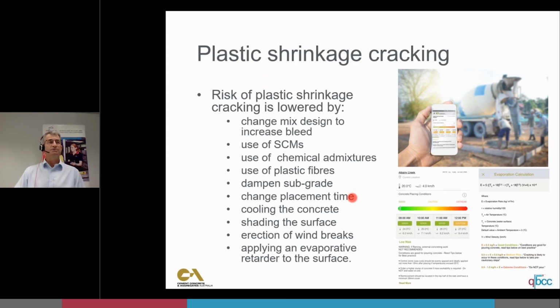So you can also reduce the risk of plastic cracking by all of these things. Having a higher bleed, using SCMs like slag and fly ash, use of chemical admixtures, plastic fibers. Plastic fibers, particularly the microfibers, help prevent plastic cracking. Dampen the subgrade. Remember, we spoke about dampening the subgrade, particularly if you're not using plastic, so the water doesn't get sucked down into the ground. You want the water to go up as bleed water to the surface of the concrete.